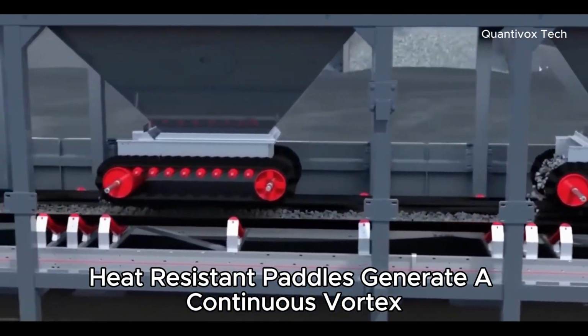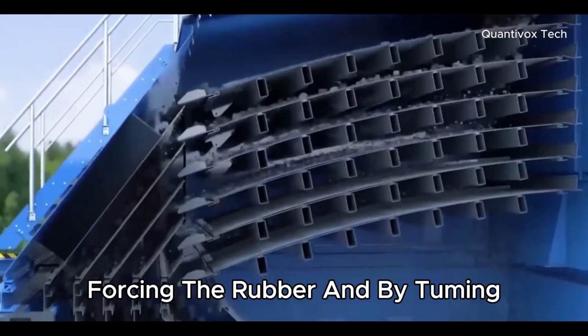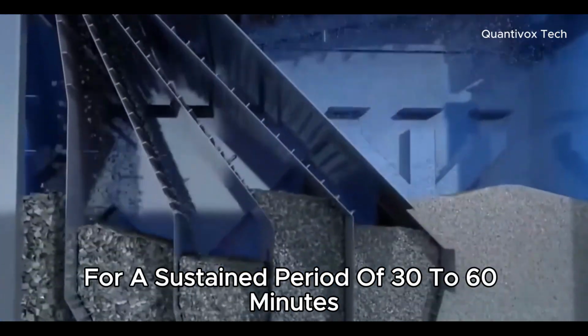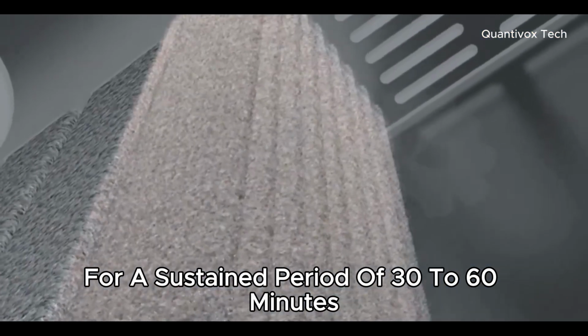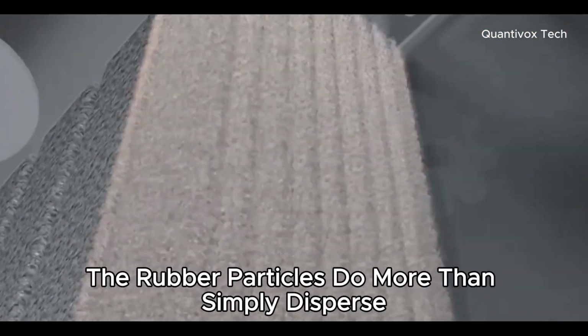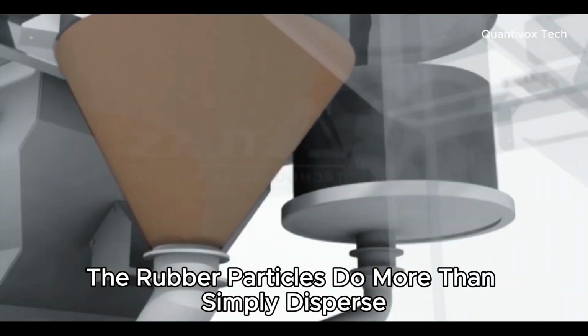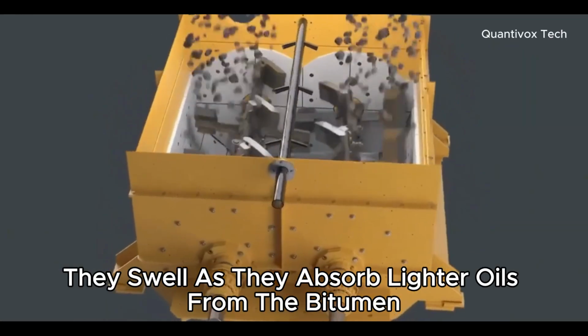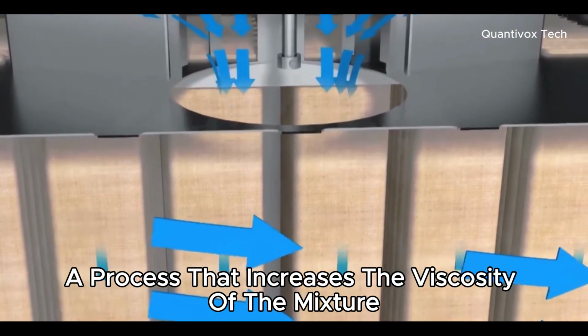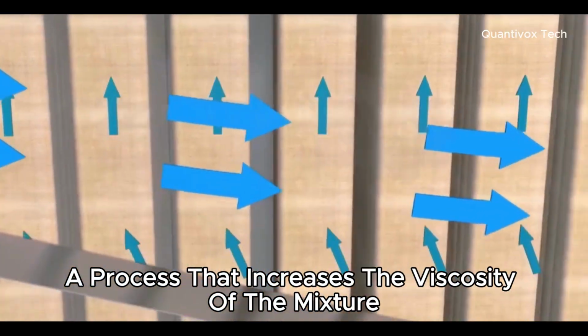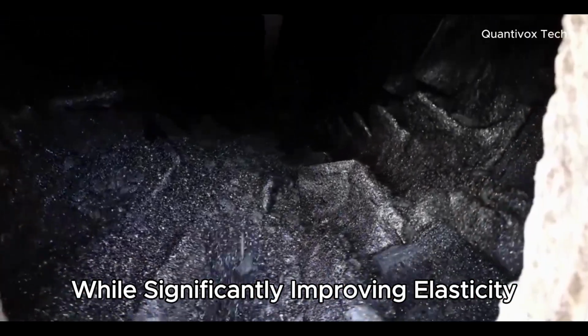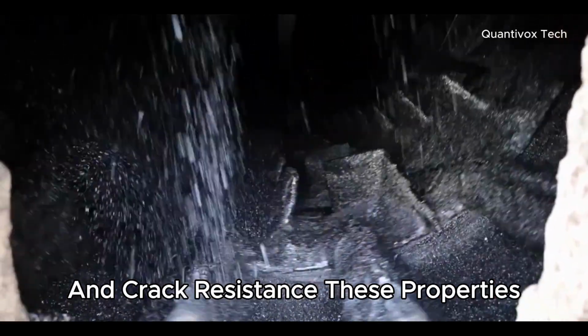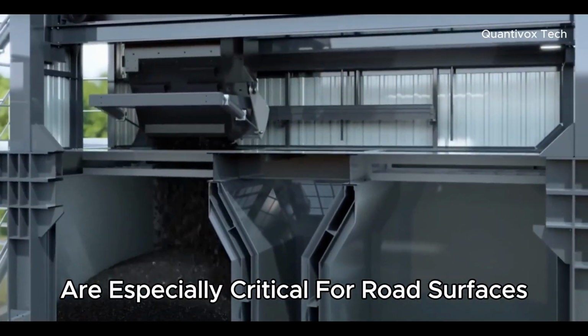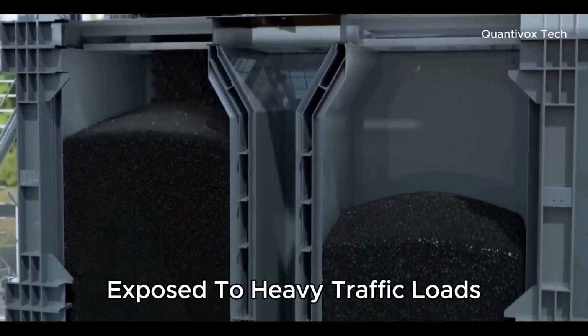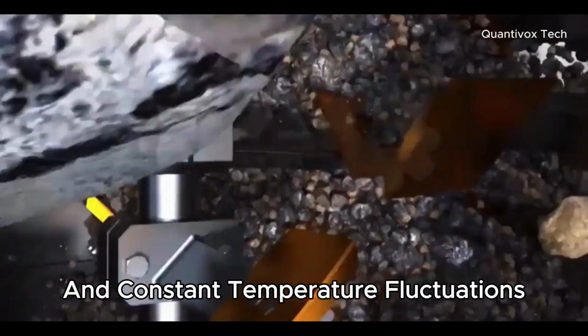Inside the mixing unit, heat-resistant paddles generate a continuous vortex, forcing the rubber and bitumen into intense contact for a sustained period of 30 to 60 minutes. During this time, the rubber particles do more than simply disperse. They swell as they absorb lighter oils from the bitumen, a process that increases the viscosity of the mixture, while significantly improving elasticity and crack resistance. These properties are especially critical for road surfaces exposed to heavy traffic loads and constant temperature fluctuations.